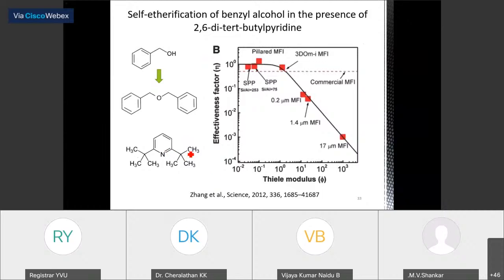For example, if you react one benzyl alcohol with another molecule of benzyl alcohol in the presence of acid sites, you can generate this dibenzyl ether. These are all probe reactions. Okay? Some of the organic chemistry colleagues, they will think that it's a simple reaction, but it is a probe reaction for probing the acid sites as well as the influence of pore size. People working in zeolite catalysis, they will use this kind of simple reactions which are having bulky molecules, reactants, and products.